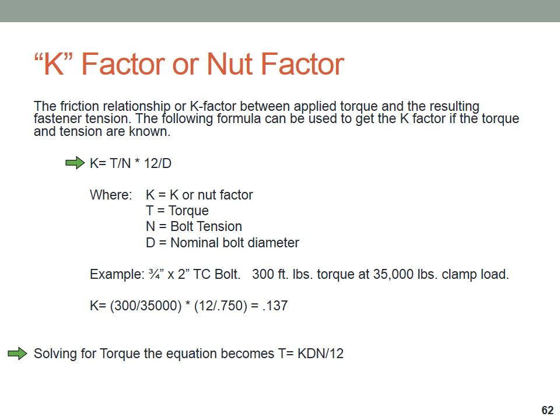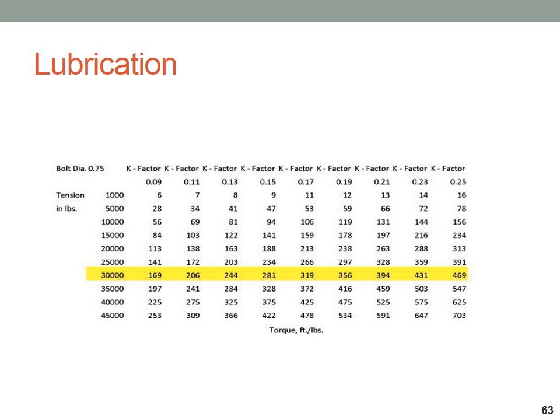The reason I bring this up is we get questions pretty much every week, and I'm sure AISC gets a lot of these: what torque should I install a 3/4 by 4 inch bolt to? And we sort of laugh because in the real world we have lubricants and coatings that are down as low as a 0.09 K factor. And we have dry bolts out of the keg that have had most of the oil sort of drip off, and we typically on any given fastener assembly could see anything from a 0.09 to a 0.25 K factor on any given day. And what does that mean for torque now?